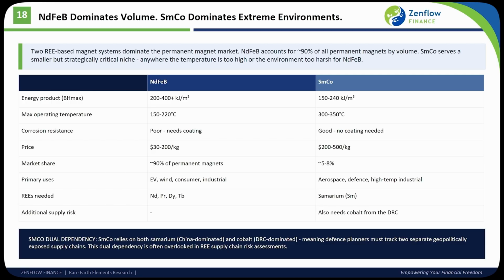But here's an important wrinkle highlighted at the bottom of the slide. SmCo has a dual dependency. It requires samarium, which is China dominated, and cobalt, which is DRC dominated. So defense planners and analysts tracking SmCo supply chains must track two separate geopolitically exposed supply chains simultaneously. This dual dependency is frequently overlooked in the mainstream RE supply chain risk assessments.